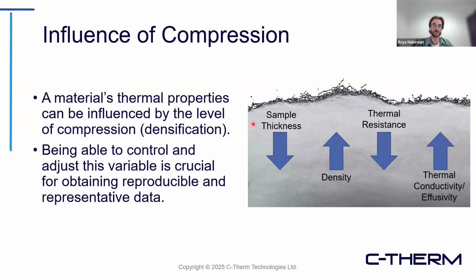One of the really interesting things that we see groups looking at is the impact of compression. If you are going to densify your sample, apply a certain force on the material, or maybe in application it's compressed by a certain degree, this can impact the effective thermal conductivity based on the inherent changes in the density of that material. As you push down on the sample, its thickness changes, but it's also increasing in density, which has a correlating effect of decreasing the thermal resistance, increasing conductivity and effusivity. So being able to control for one of the variables, the compression of the sample, can be really useful in getting really comparable data, especially if you're trying to find which is my best material to use in a given application. We want to, one, test them in a similar way, but then also ideally represent the end use case. So we're really doing that apples to apples comparison.